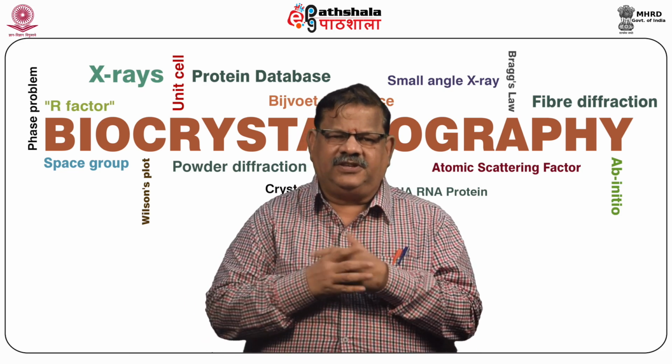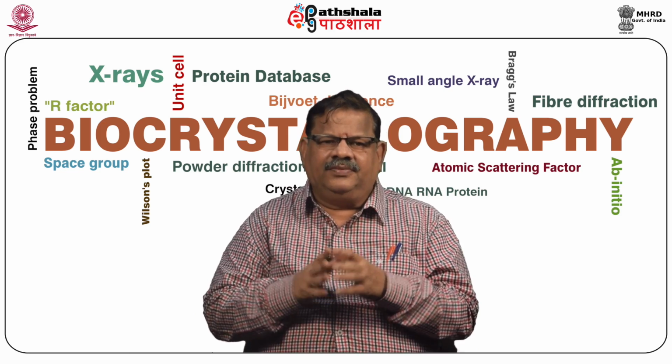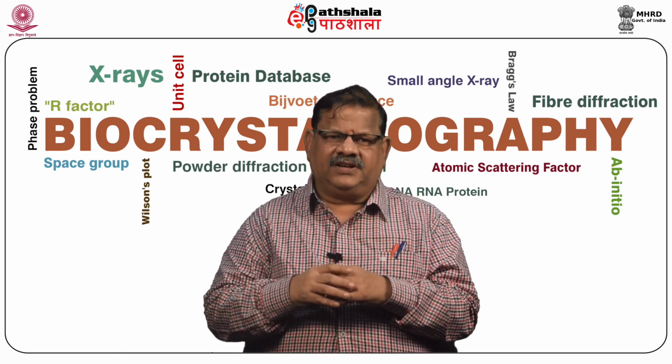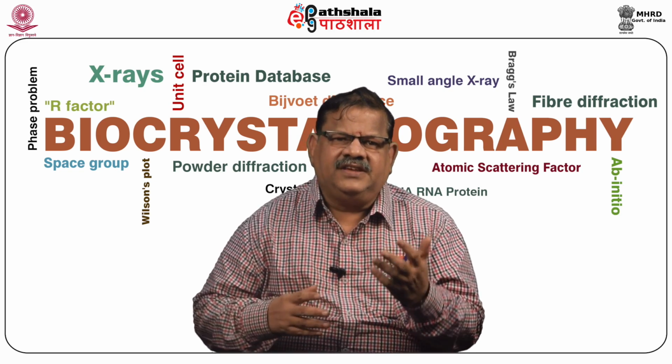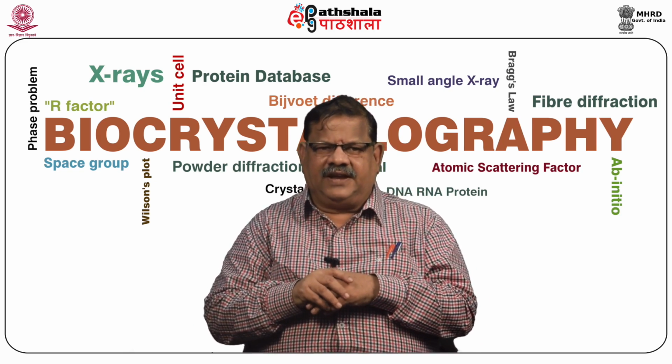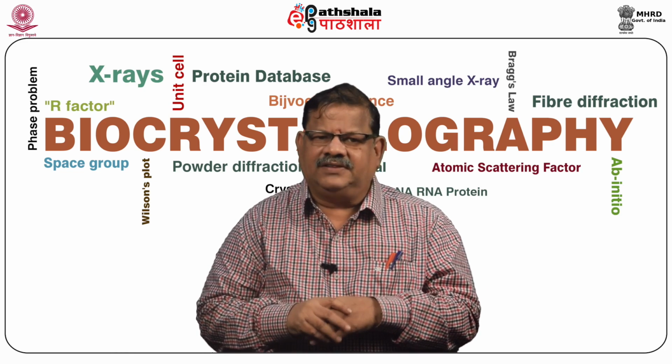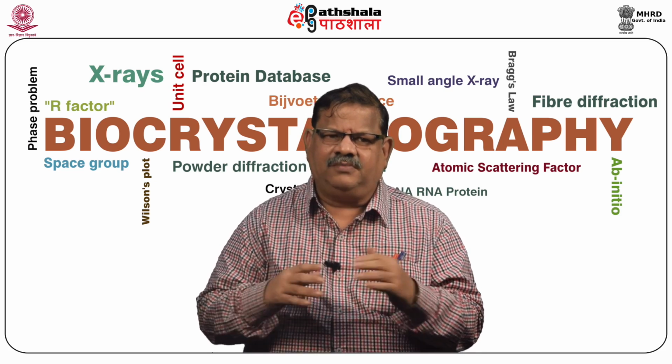What do you mean by a dispersive difference Patterson? Here, the differences between the structure factors of the same reflection arise due to the change in the real part of the atomic scattering factor corrections. So this is done in the case of the multi-wavelength anomalous diffraction technique, which is known as the MAD technique.